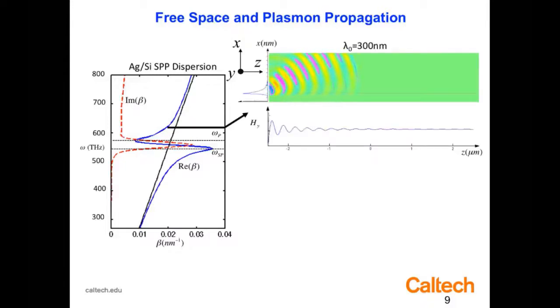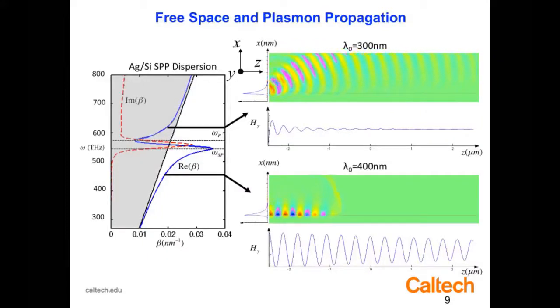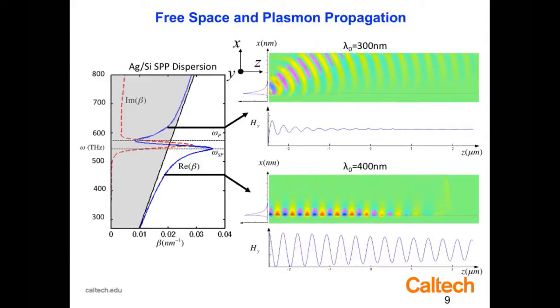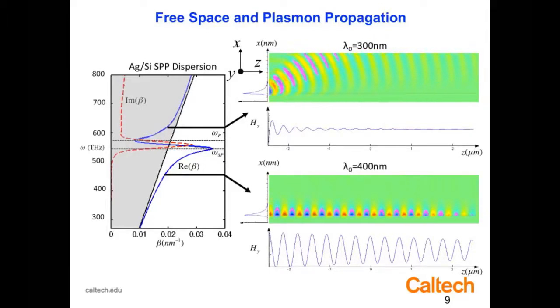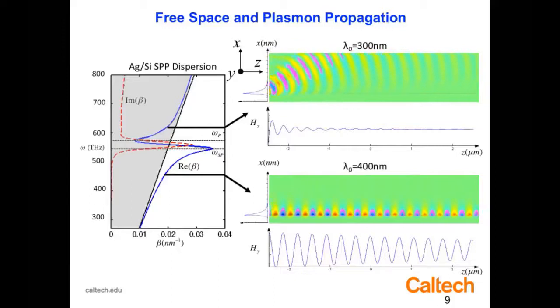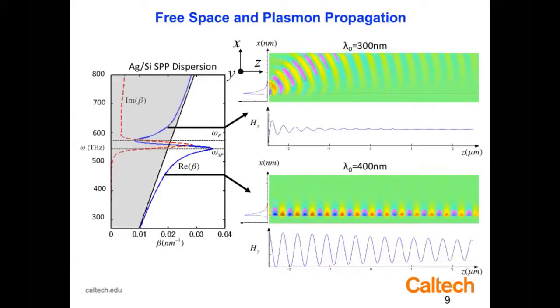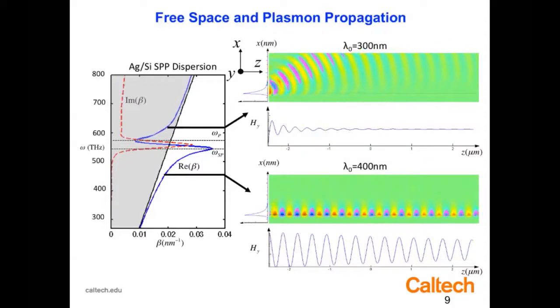So if I excite at a frequency up here, you can see even if I excite with light very close to the metal dielectric interface, the light goes into the air basically and just radiates into free space. It's unbound. We don't see any mode on the surface. However, if I now excite it down here where the dispersion relation lies to the right of the light line, then I get a bound mode. And as I excite the metal surface, I get a wave that propagates along. You can see the amplitude of the wave is going down a little bit, but it's a smoothly propagating wave bound to the surface.